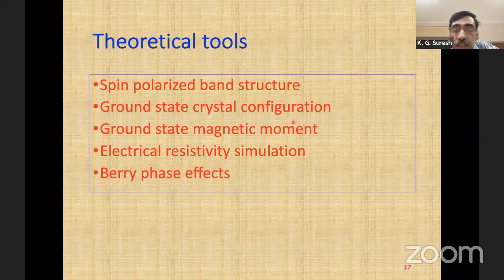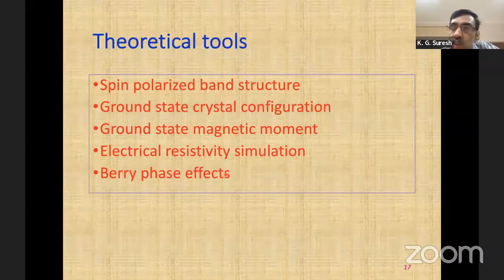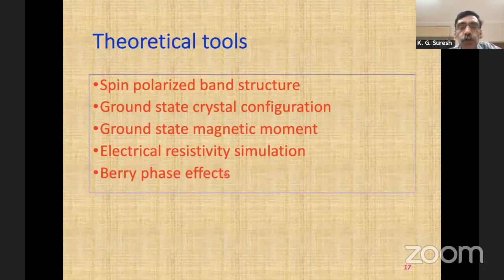Electrical resistivity is not that simple using a DFT kind of thing, because you have temperature effects coming there. And very importantly, for topological and spintronic aspects, Berry phase effects are very, very significant. This is a very hot topic today. People have to really calculate. It's a very expensive calculation. One does it, and then you try to compare with, for example, the anomalous Hall effect and so on. Then only you will be able to get some idea about the band structure, which is very, very crucial to get an insight into the material.